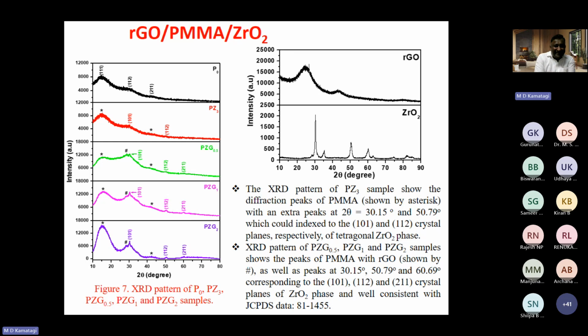And then this is the case. This is the composite film: polymer, nanoparticle, and the graphene oxide. So we can see the peak corresponding to graphene oxide as well as the peak corresponding to ZrO2 and the PMMA.